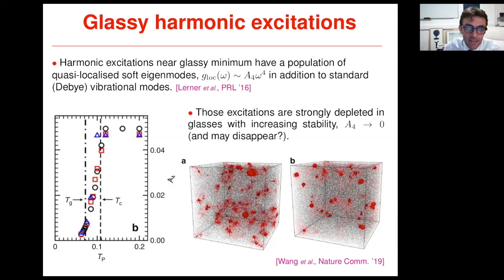quasi-localized mode as the preparation time of the glasses increases, as we prepare better and better glasses, these excitations are strongly depleted when we increase the stability of the glass. And this is shown here where this prefactor in the density of states is shown as a function of the equilibration temperature of these glasses. So we see that this prefactor, which was relatively high at high temperature, decreases sharply as the temperature decreases and almost vanishes at extremely low temperature. So we may suspect or conjecture that maybe these quasi-localized harmonic excitations are going to disappear when we approach nearly ideal glasses.